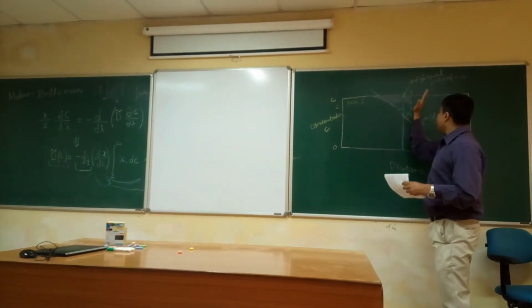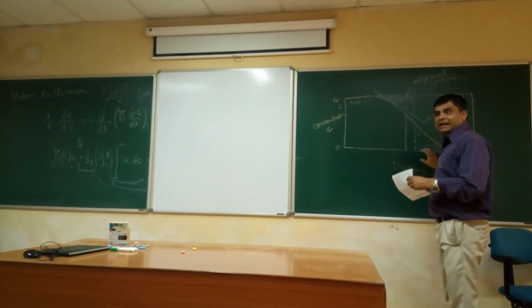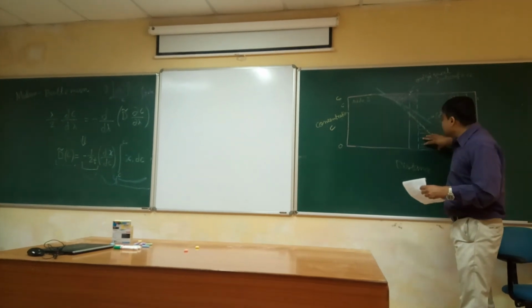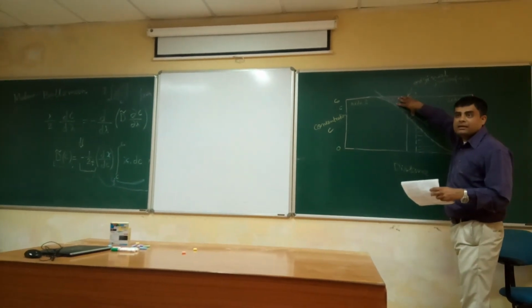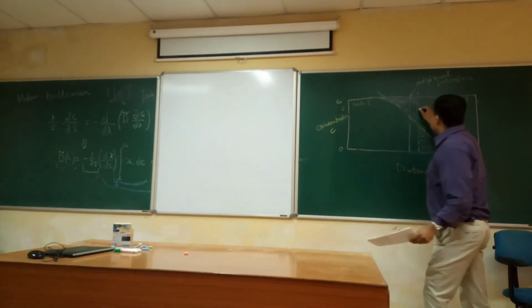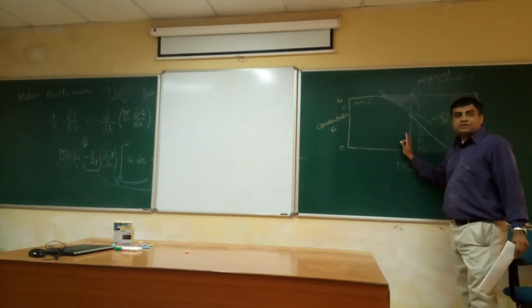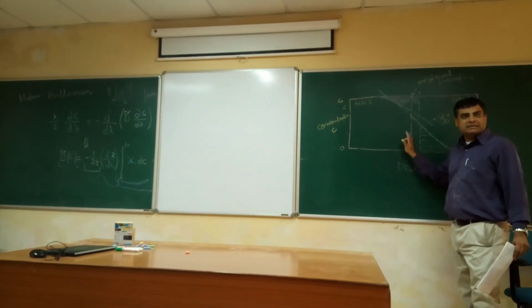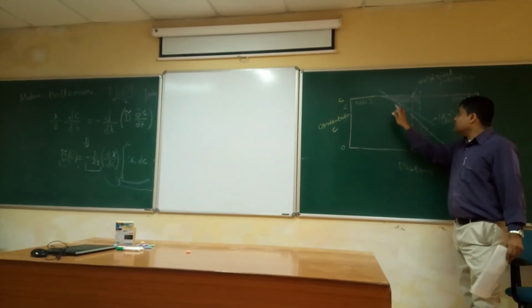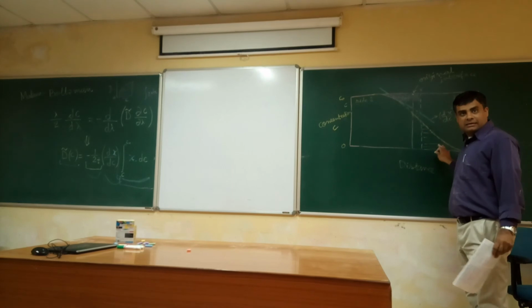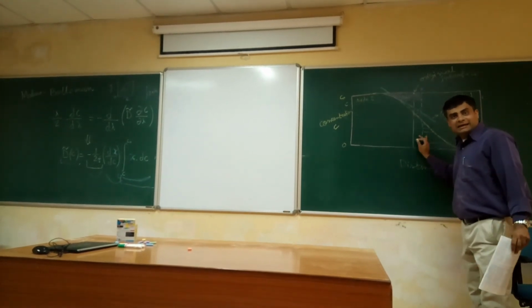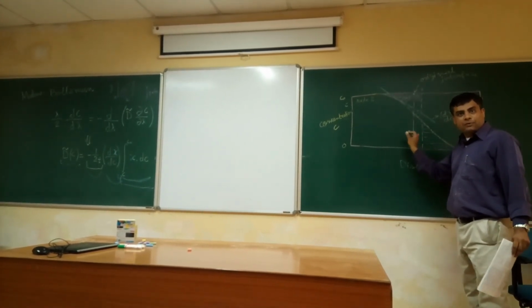So across which plane can the shaded areas be equal? This area and that area will be equal. Across your original interface, this is not symmetrical, so this area was less than that area. But across some other interface, these areas are equal.